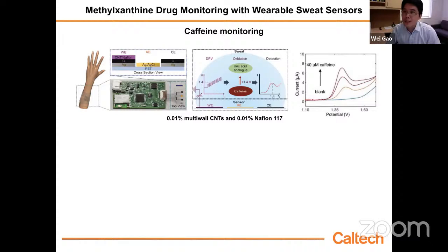And we can detect the caffeine using differential pulse voltammetry. As I said, caffeine is an electroactive molecule, as I mentioned earlier. If we use the carbon working electrode, we can detect caffeine at around 1.4 volts. The oxidation peak height has a linear relationship with the caffeine concentration.